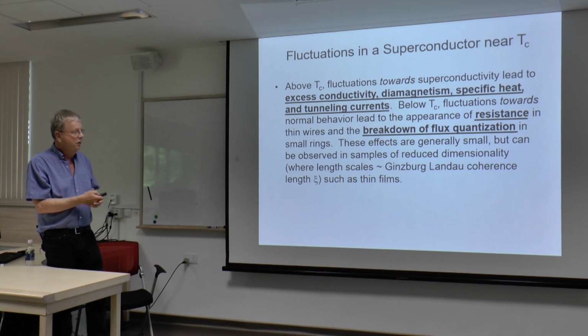So above TC, you can have fluctuations that give you an excess conductivity. So resistivity is a little low. Gives you some diamagnetism, which is a lead-pipe cinch to measure. Gives you an effect in the specific heat, which is my field of expertise. And you can have some tunneling currents. Below TC, you can have these other kinds of fluctuations. And when you get into thin films, you're just into fluctuations.